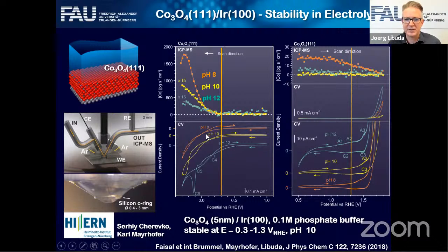And you always measure the currents together with the dissolution rates. The message from this experiment is that if you stay within the right potential window and choose the right pH, the dissolution rate is actually below the detection limit of this experiment. And I mentioned at the beginning, the detection limit of this experiment is quite impressive. It's somewhere in the range of percent monolayer per hour. So we really have practically no dissolution of this film under the conditions of the experiment.